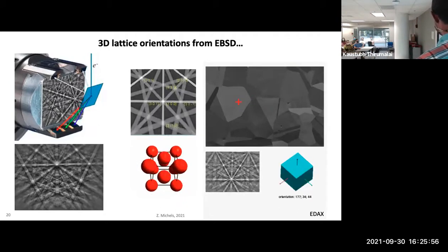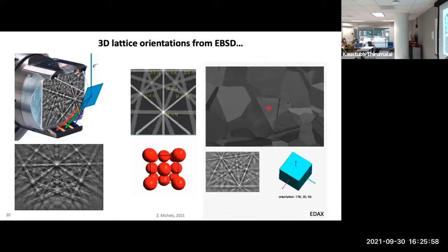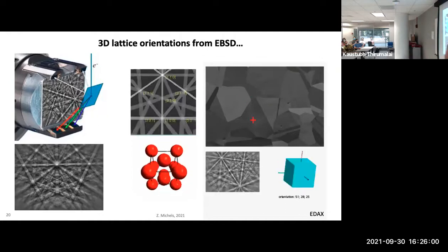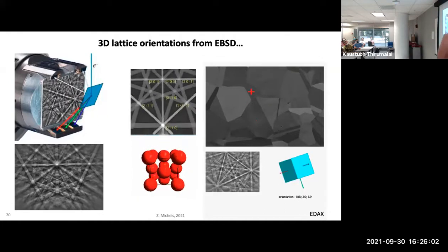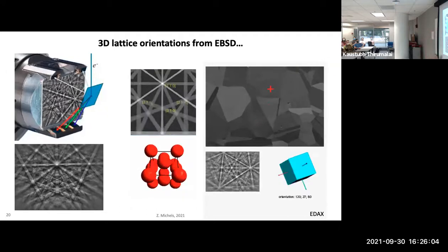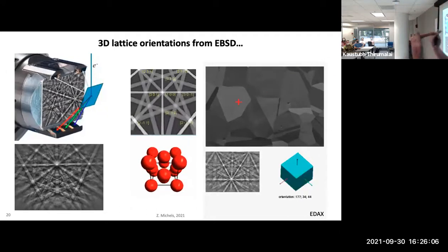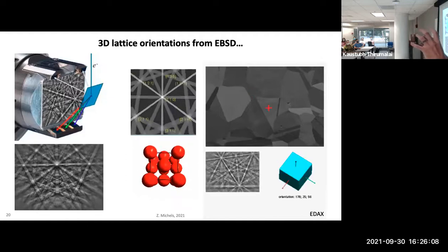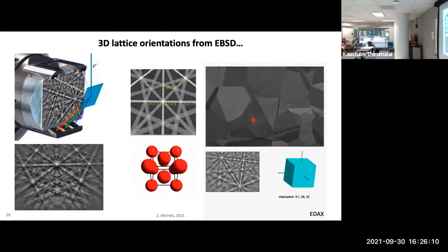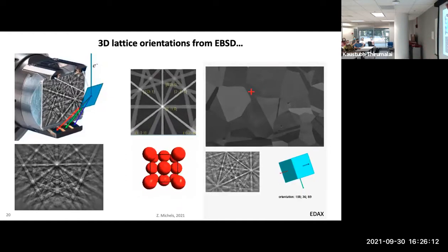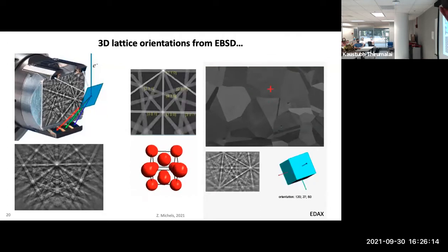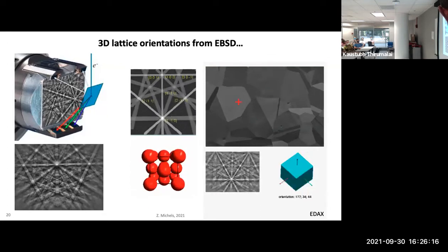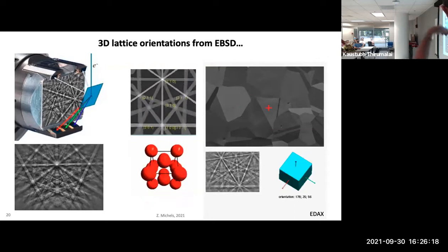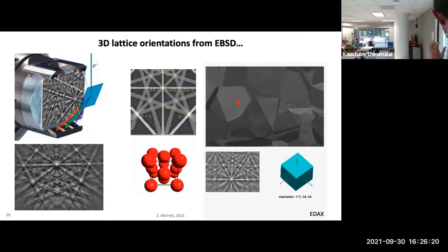And those electrons hit this phosphor screen, and the bright spots are where you're seeing more electrons hitting the screen. And what that's actually doing is showing you something about the lattice structure of that spot that it's interacting with. And so here's an example from a cartoon that EDAX made of a rotating lattice and how those bands would change if the lattice orientation was changing.